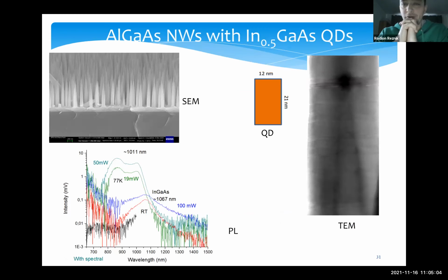Also, these are very latest results. To increase the number of applications for such structures and to increase the wavelength range of quantum dot emission, we tried to form indium gallium arsenide quantum dots inside aluminum gallium arsenide. So by changing the indium content and size of these quantum dots, hopefully we can change the energy of emission and maybe reach 1.3 microns as well, 1.3, 1.5.